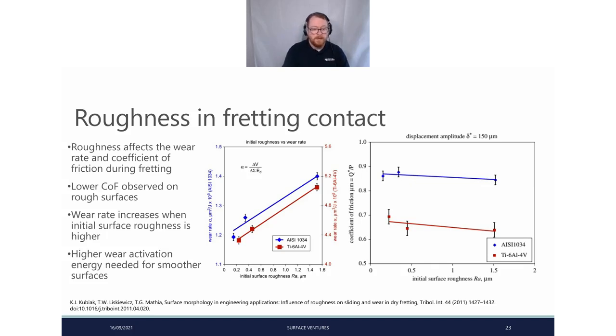And I'd said earlier, roughness in fretting contact. Another great paper here by Kubiak looking at roughness and how this affects the wear rate, as well as coefficient of friction. So with our initial surface, this is of course initial surface roughness. Again, tribologically transformed structure, the roughness will change throughout this. As roughness increases, coefficient of friction reduces. Conversely, as roughness increases, wear increases.